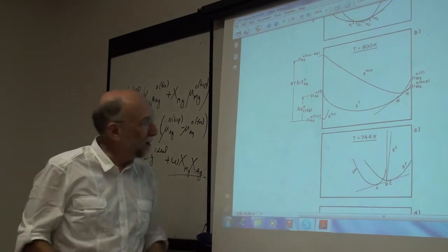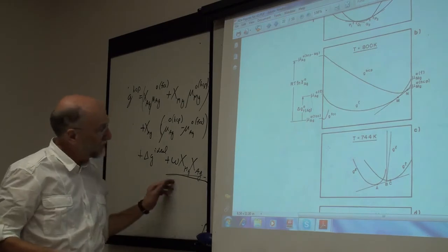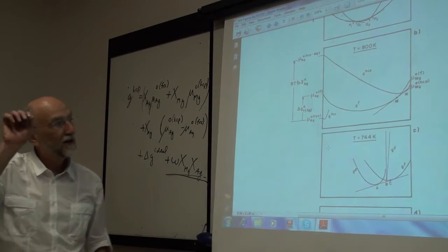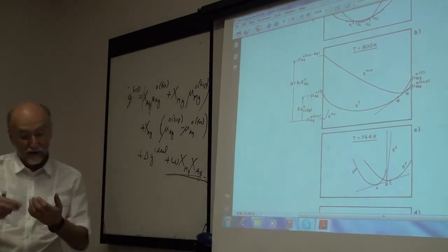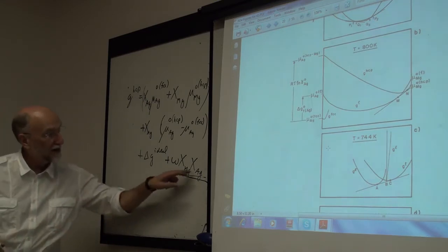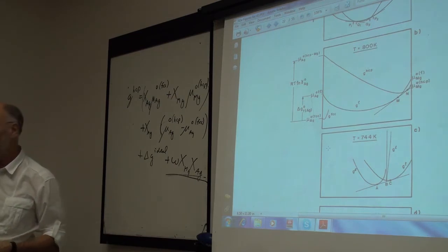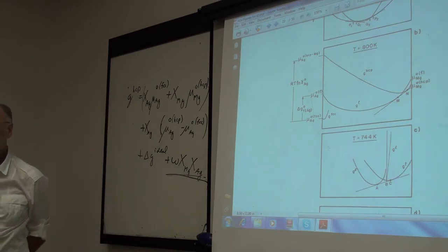Okay, so remember the excess, why do we have this term? Well, it's because in the limiting region, every time you add a silver, every silver goes in entirely surrounded by magnesium. But after the silver concentration gets high enough, a silver sees another silver, and that ends up giving you a quadratic thing, just like the regular solution theory. So this is a reasonable way to fit this type of curve. That's the way we usually do it. Okay, everybody happy with that?